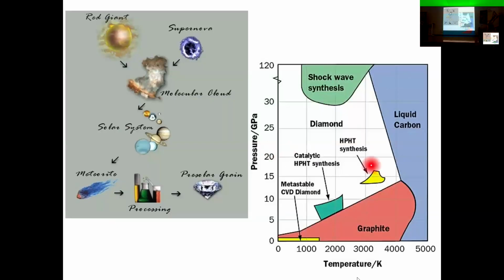But you can see that synthesis of diamond can be obtained in this HPHT process, so high pressure, high temperature, but also here in low temperature and low pressure. And we do that at Lodz University of Technology in the Material Science Institute. So it is a group where, in the chemical vapor deposition process, CVD, the plasma-assisted CVD process, diamond coatings can be manufactured from methane.